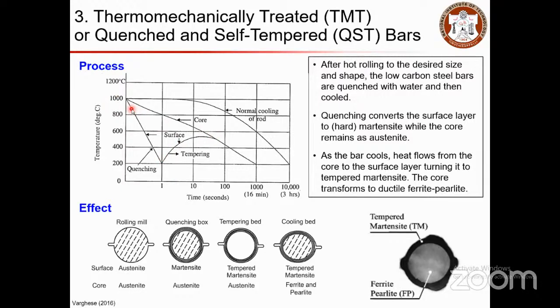By doing this process, you can see the effect of the whole temperature process here. After rolling, both the surface and core material will be austenite. In the quenching box, what happens? Your surface is immediately quenched, so that becomes martensite, and your core will still be in the austenite stage. When it is kept in the tempering bed, the temperature is slowly going to emanate from the core to the surface. So the martensite will become tempered martensite, and your core will still remain austenite. When you do a cooling process, the tempered martensite will still be the same, and slowly the coolness will be disseminating through, so the core becomes ferrite and pearlite.